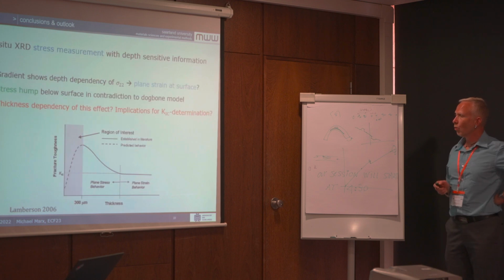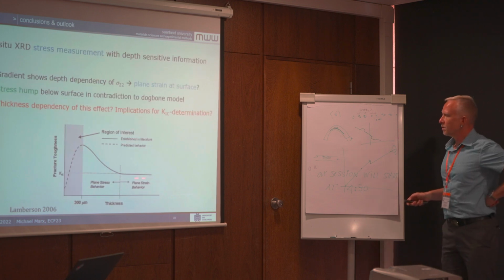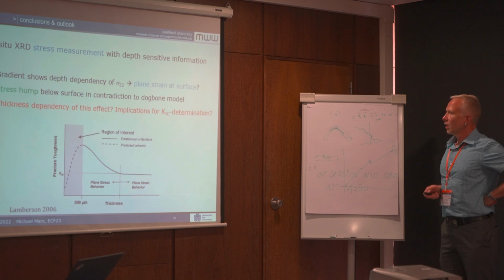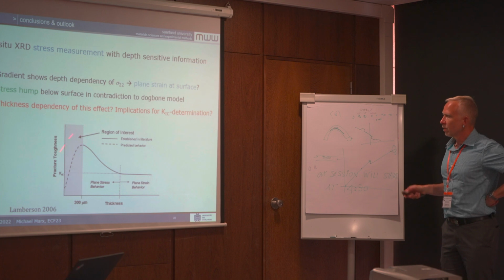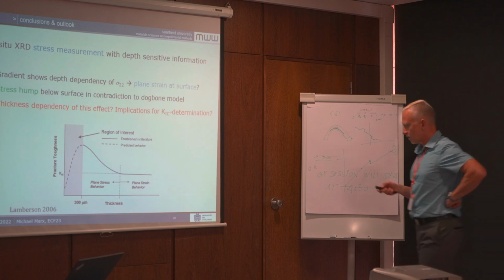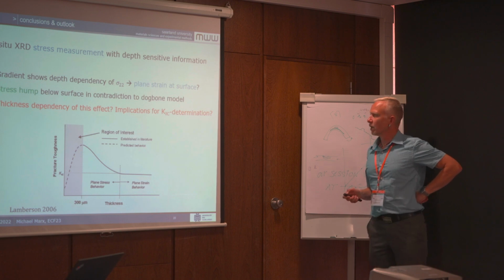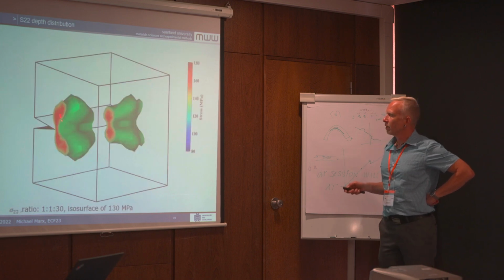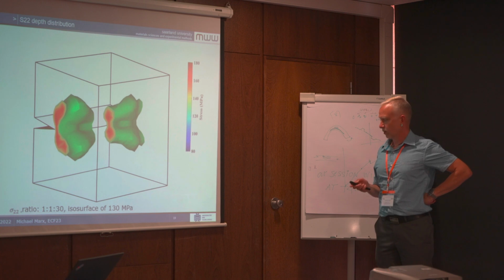Yeah, and now we think, this is what I have shown at the beginning, the fracture toughness as a function of the thickness of your specimen. This here is well known. Here we have the area where we measure K1C, and then we have the increase of the fracture toughness, and here in this region of interest, what happens if you go to a very thin specimen? Maybe this can be explained by this behavior of the plastic zone.